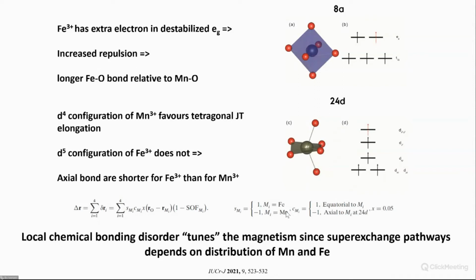But more importantly, when you move the oxygens around, of course, you change the superexchange pathways through the structure. So by introducing the manganese and iron disorder here, you also change the magnetism. Ultimately, it would be fantastic if this is really a handle to tune the magnetism. We've not been able to synthesize these. These are all natural crystals. It's not so easy to make big crystals of Bixbyite.